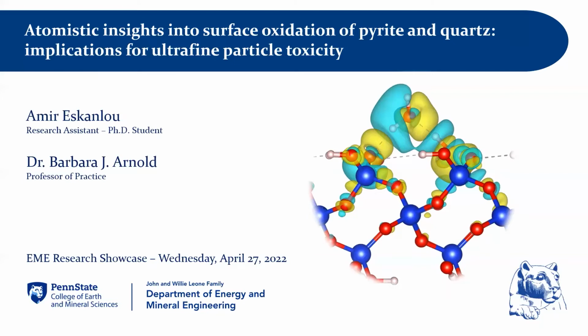And then in conclusion, the adsorption of water molecules on the surface of quartz is slightly more thermodynamically favorable than oxygen. Such interactions entail the formation of SiOH, the free silanol, and hydroxyl radicals and peroxyl defects. If you ask what peroxyl defects are, this is a peroxyl defect. This is a peroxyl defect as a result of oxygen interaction with a quartz surface.